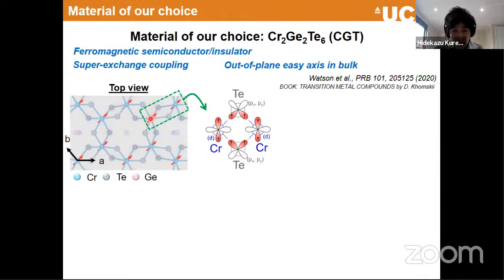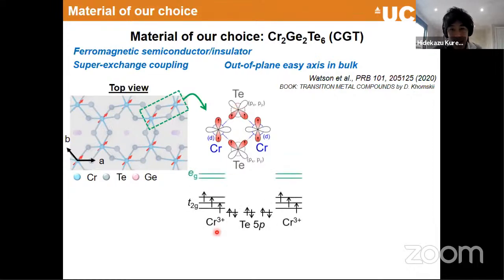So when we pick, let's say, these two chromium atoms and two tellurium atoms, because of this octahedron bonding, and this is corner shared, the angle between these two is pretty much close to 90 degrees. And chromium has, as I already explained, a 3+ ionic state, and tellurium has a 5p state here.